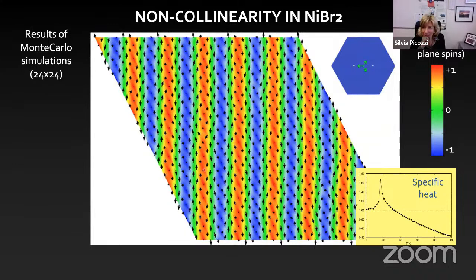So in nickel bromide, what do we get? You see here, maybe not so clear, some black arrows which change, and also the out-of-plane component is moving from side to side, which means that basically we have a helix propagating along this x-axis. So it's a spin helix. The spin rotates in a plane which is perpendicular to the propagation direction. And so you see here from this spin structure factor that it's actually a helix, right?